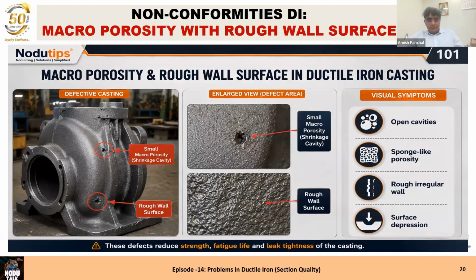Excellent. Here we can see some examples of it on a pump casing, and we can see a macro porosity and a detail from it. It's small, but it's macro porosity, and under it there's a rough wall surface, but that's not the porosity, of course. And we can have an open cavity when the porosity comes to the surface. We have sponge-like porosity, rough irregular wall surface, and surface depression, as already said. A porosity will reduce the strength and fatigue life, but mainly also leak tightness if it's used in castings like a pump casing or a valve or whatever.